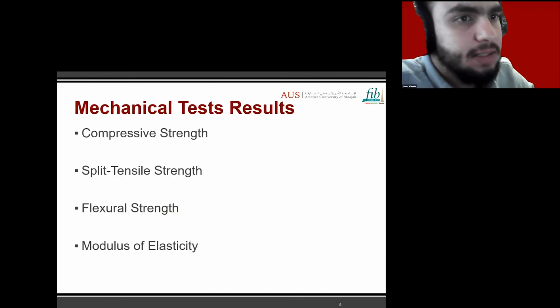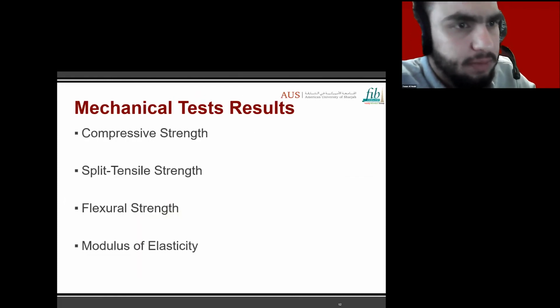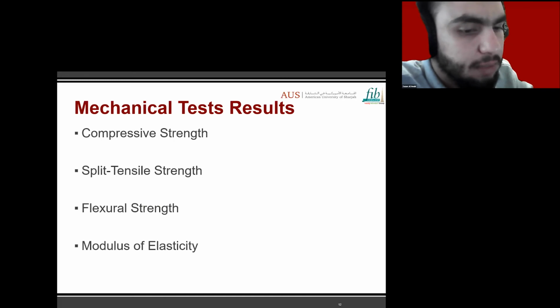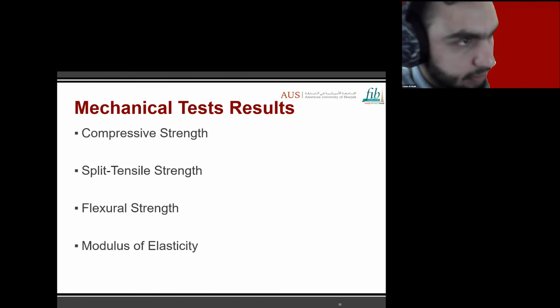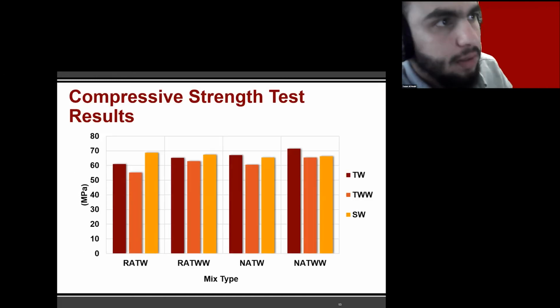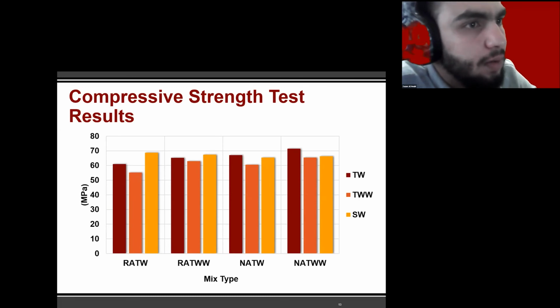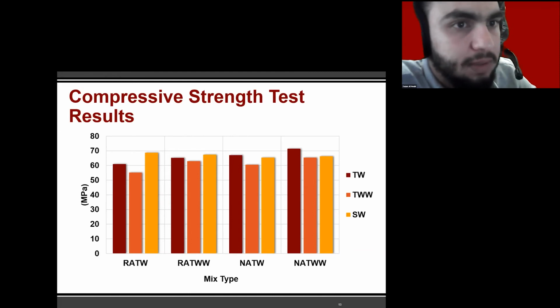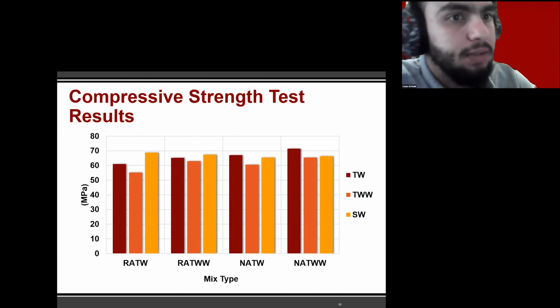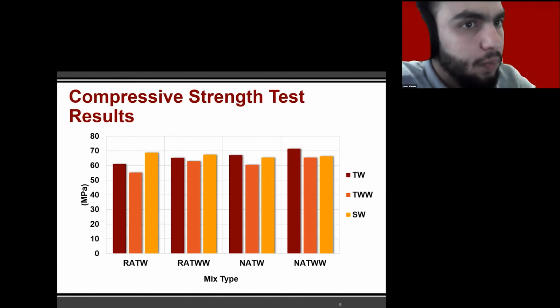The mechanical tests that were conducted in this research were the compressive strength, the split tensile, the flexural strength, and the modulus of elasticity. Some of these results will be discussed in this presentation. Looking at the compressive strength, all mixes have comparable and very close results, with reduction or improvement of strength up to 10% maximum.